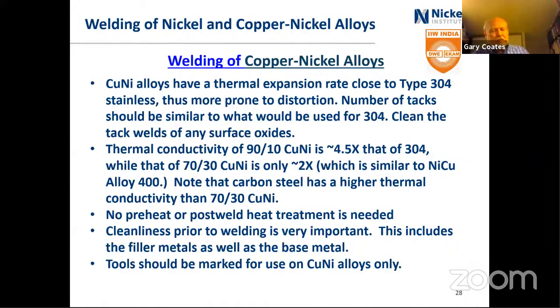Most of the copper alloys do have, as you can imagine, a higher thermal conductivity. They suck away the heat better. The 90/10 copper nickel has a thermal conductivity maybe 4.5 times that of 304. So you have to be aware of that. The weld metal will cool faster than it would on a stainless steel. For the 70/30 copper nickel, it's 2 times that of 304, and almost identical to the alloy 400. So still better than stainless steel, but not as good as the 90/10. So again, the weld pool will cool faster than with the stainless steel, but not as fast as the 90/10.